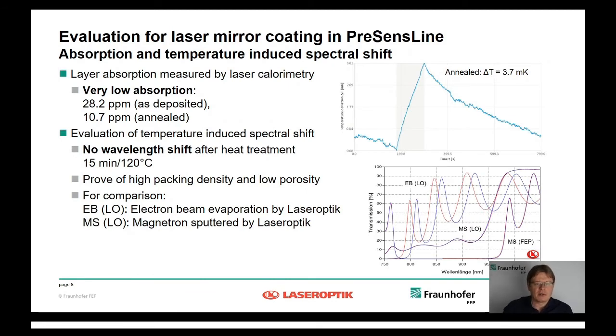Laser-Optic measured a very low absorption, something like 11 ppm, from the annealed layer system. The wavelength shift was very low. Here in this graph you see the results of three different layer systems. This is our system, so almost no wavelength shift after the heat treatment. The same is true for the Magnetron sputtered layer system from Laser-Optic.